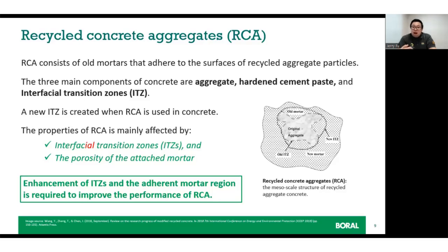So the aggregate-cement interfacial zone consists mainly of loose and porous hydrates. Since the difference in properties of recycled aggregates with respect to natural aggregate is mainly driven by the presence of the old attached mortar on the surface of the recycled particle, the residual mortar is responsible for the lower specific gravity, high absorption, and low abrasion resistance of these recycled aggregates when we compare them to natural aggregates.